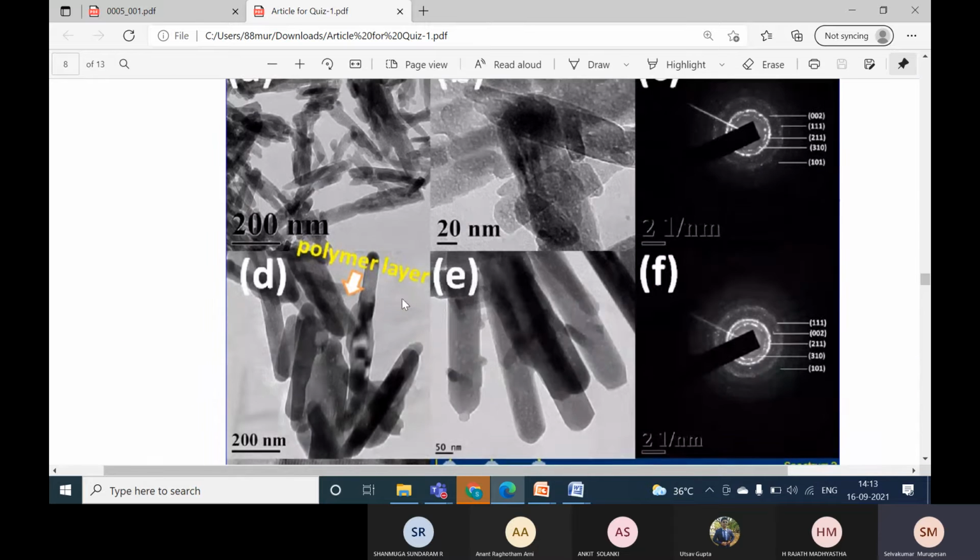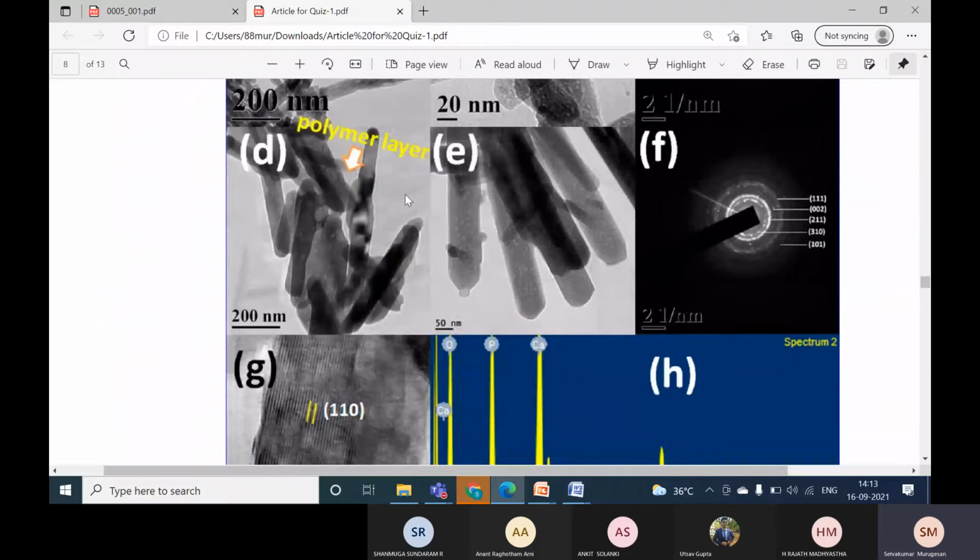So these are a few things where you can play around with the surfactant and their structures. Here the mechanism was a mixed hypothesis: the structure also plays a role because it has a hollow structure. When you dissolve the beta cyclodextrin inside the precursor solution, the crystal starts to form around that cone or hollow structure. Then once you do the calcination, the template, the beta cyclodextrin, will start to decompose. As a result, the void will start to form.